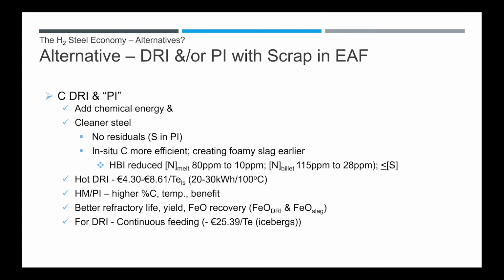Of course, the other alternative is to definitely look to the future using alternate irons with the scrap, because it will add chemical energy and you will have cleaner steel. Nitrogen is not going to be a problem. It can be reduced down to 10 ppm for melt and 28 ppm for billet. You also have, if you're charging hot, a lot of benefits financially and energy-wise. As you can see, 20 to 30 kilowatts per 100 degrees C. Same for hot metal and pig iron. And you have a better refractory life, yield and FeO recovery. And of course, it can be continuously fed, as can the granulated pig iron that's now being looked at seriously. Next, please.